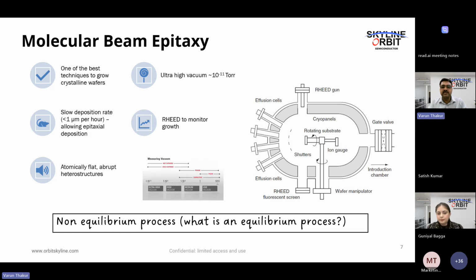These are the effusion cells which hold the material, and we pass current. The wires are of course not shown here, this is a schematic. This increases the temperature of the cells, and so the temperature of the material inside, and it evaporates to deposit the film on the substrate. So what are the materials that we are depositing? They are controlled by these shutters. Whichever shutter is open and the temperature is high, that material will deposit.